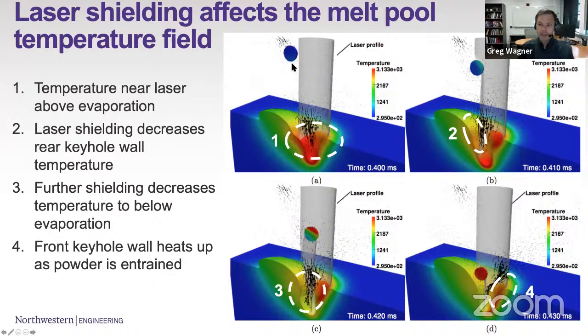In a time sequence, as the powder particle moves into the laser, it causes a decrease in the temperature here in this region number 2 that reduces the evaporation, reduces the temperature, and causes the keyholing to be lessened a little bit. Once the powder is then entrained into the laser, the keyhole will start to reform and we'll start to get that evaporation again. And this is a phenomenon that's been seen in our experimental videos.